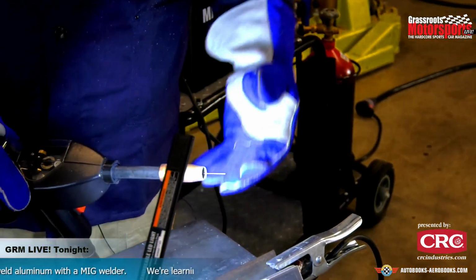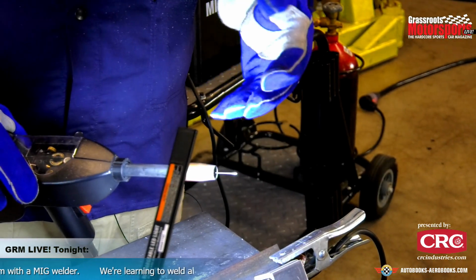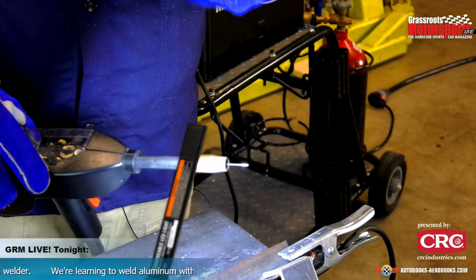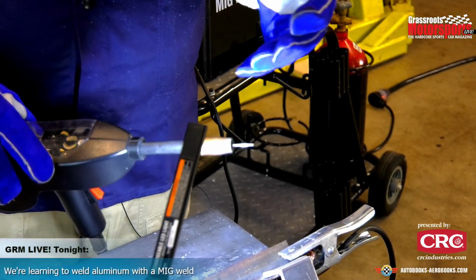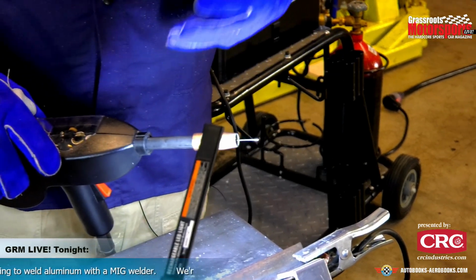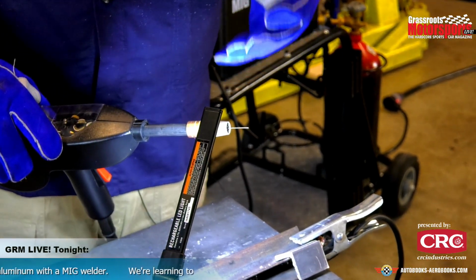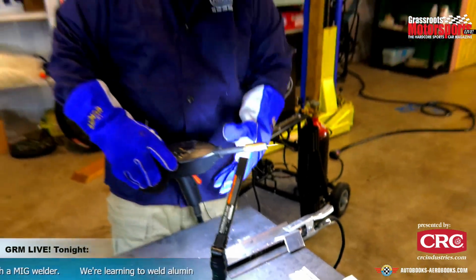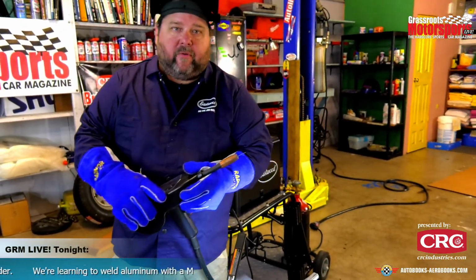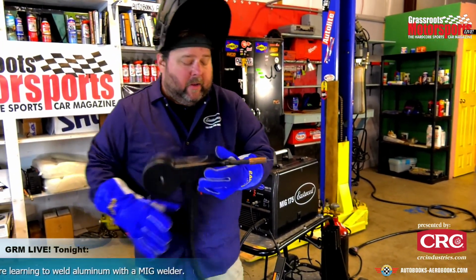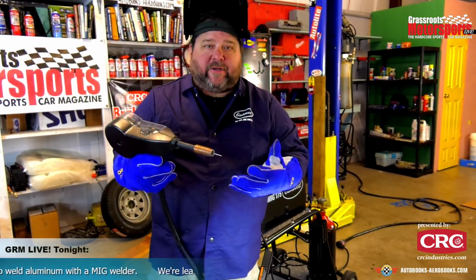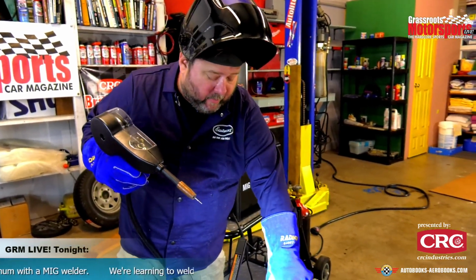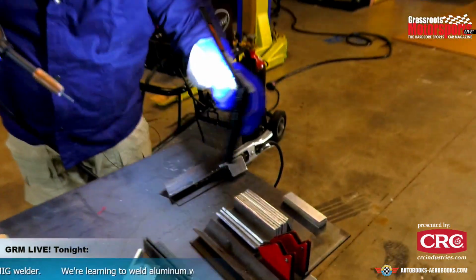Stick out is the amount of wire sticking out of the end of the gun. With steel, you're going to start about 3/8 of an inch, 1/2 an inch, somewhere in there. With aluminum, you want to basically double that. You're talking about 3/4 of an inch, up to an inch of stick out. Otherwise, you run the risk of getting a lot of burn back, where the wire actually burns itself up into the tip.